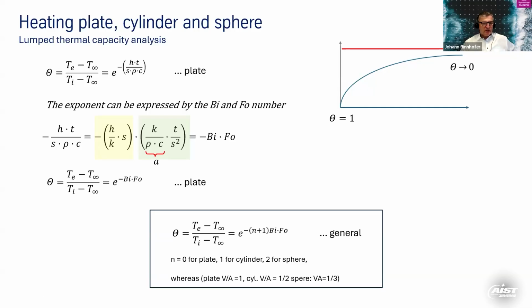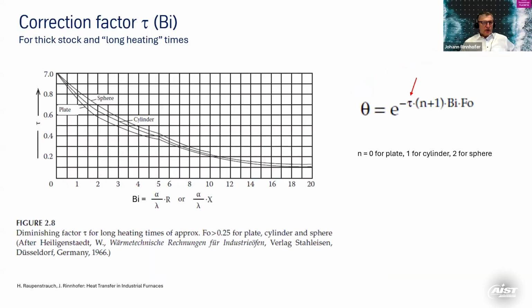What happens if you have thick stock? There's a correction factor, tau, which you can also use. This is shown in this diagram. That means a very thick body has significant temperature differences in the stock, so you have to use this correction factor, because in the end the temperature will be less. The end temperature will be less when you have a very thick body.